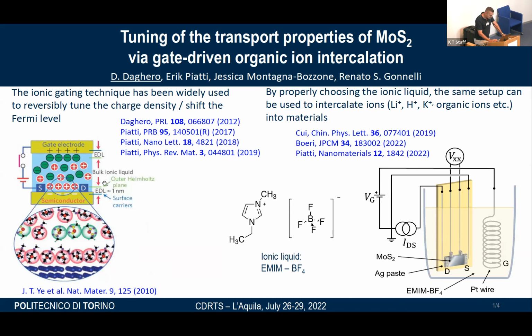This is a picture that depicts more or less a setup. It's essentially a field effect transistor in which you have a material under study. Here you have an ionic liquid, which is an electrolyte, and the gate electrode. When you apply the gate potential difference between the gate and the material under study, the ions in the electrolyte migrate and create an accumulation of charge that is, of course, reversible, in the sense that when you remove the gate voltage, the accumulation of charge disappears. Actually, by properly choosing the ionic liquid, it is possible to use the same setup also to induce a non-reversible, so a permanent change in the properties by intercalation of something.